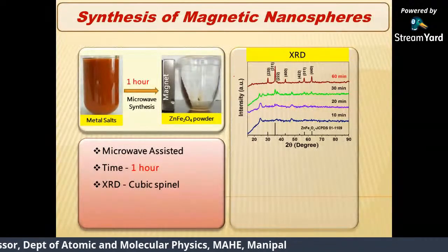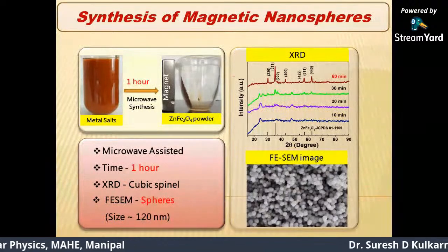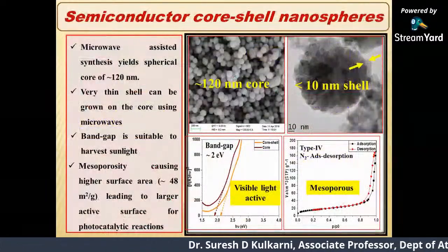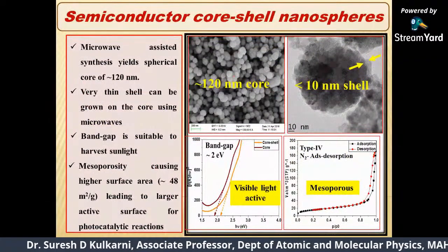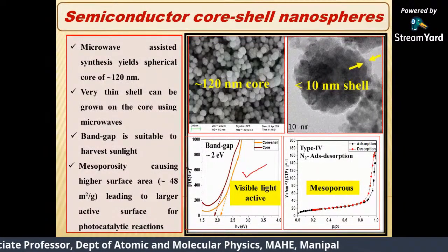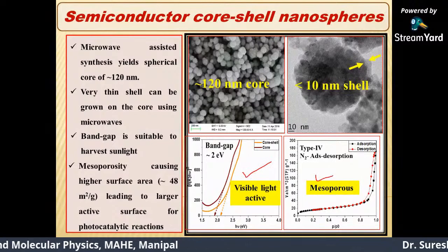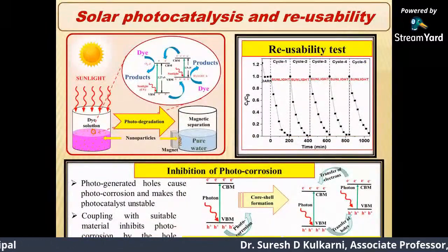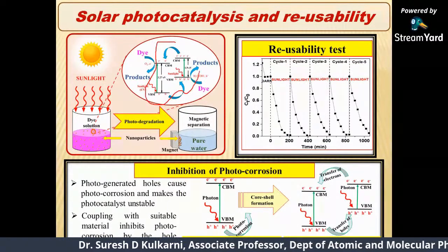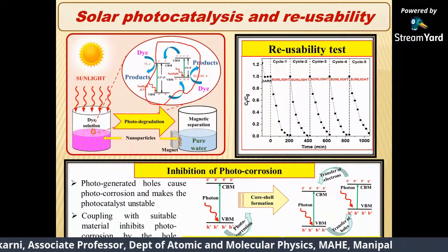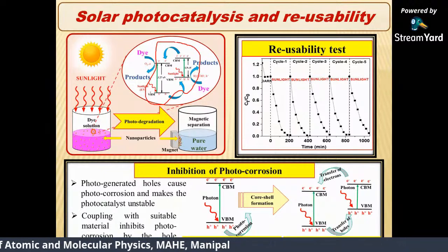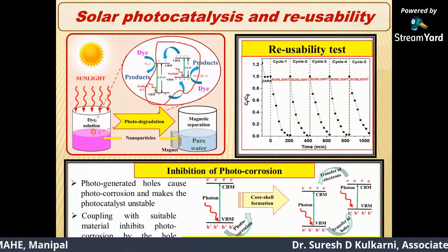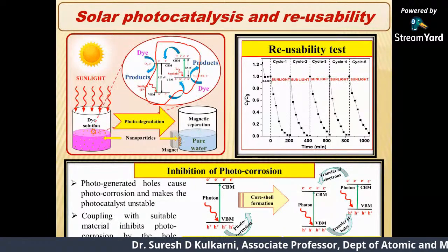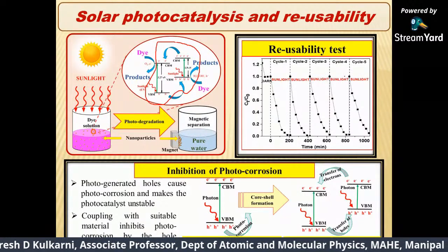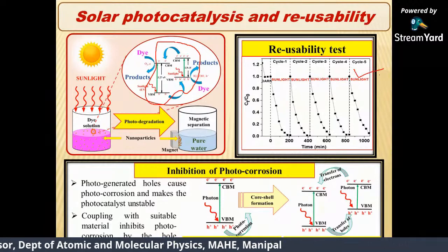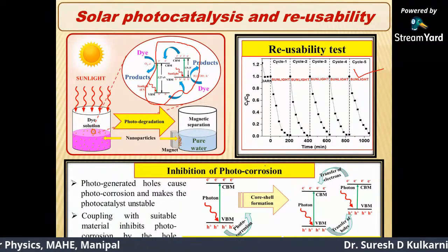Okay, so these are the materials we re-optimized, and later we have prepared nice spherical particles, and these particles are coated with a material of our interest as a shell material, and you can see that the material becomes active under visible light. This is mesoporous, and it's able to show good photocatalytic activity just because of the particular band alignment that we have been able to optimize. The bottom line here is you take a dye solution, put small amount of our particles into it, keep them under sunlight, and after 1 hour you come back and see, you will see that the solution becomes colorless. And I have shown here that up to 5 times of reuse of this material, the activity is not lost. That means there is nothing like photo corrosion.